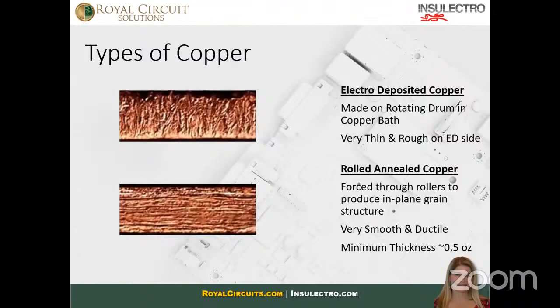So when a fracture does occur, because things fail over time, the crack follows the grain boundary. But instead of being able to go straight down to the substrate and then manifest as an open in your board, instead it sees the grain from the next copper beneath the top one and it stops because that grain has been squished and moved and that fracture can no longer follow the grain boundary as it could if we were doing an ED foil.